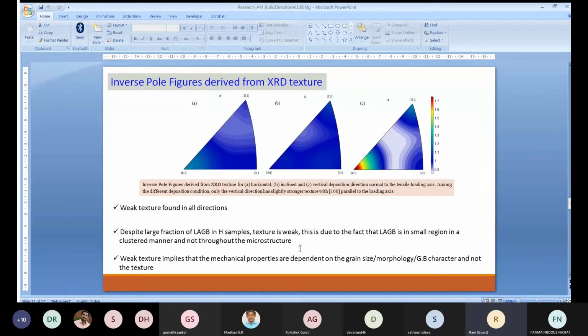And we also tried to understand the bulk texture through XRD experiments. So we have plotted the inverse pole figure here. One understanding from this inverse pole figure is that the texture is very weak in all the directions, in the horizontal, vertical, and inclined samples. Despite the large fraction of low angle grain boundaries, which would cause texture, we didn't find strong texture in the horizontal direction. It is because these low angle grain boundaries are inside the grains in a clustered manner rather than formed throughout the grain microstructure. So that made the texture weak in the horizontal samples.